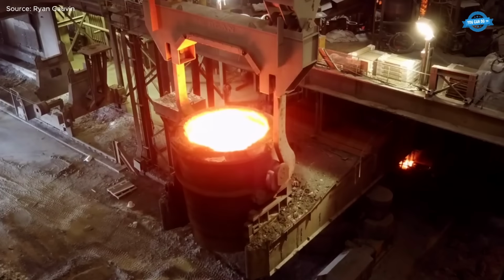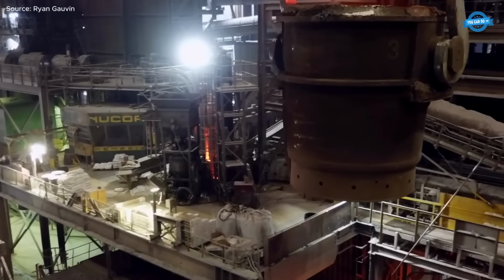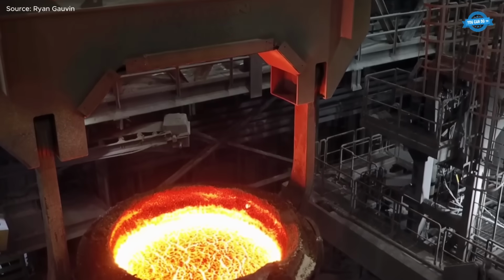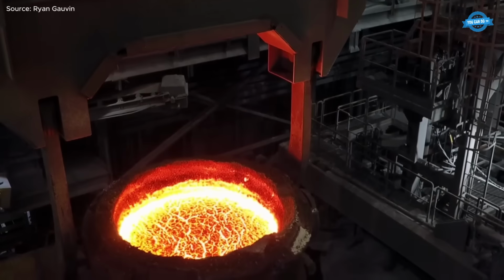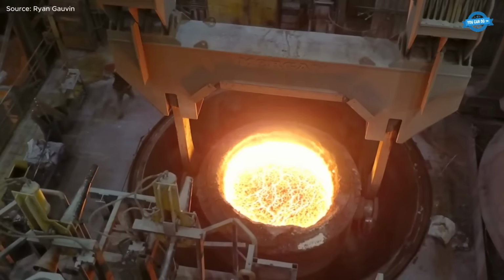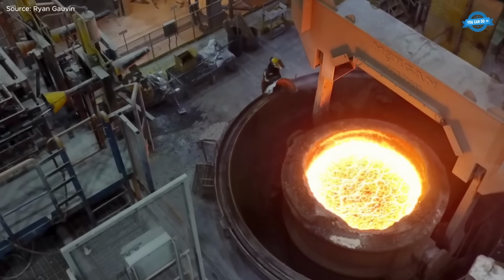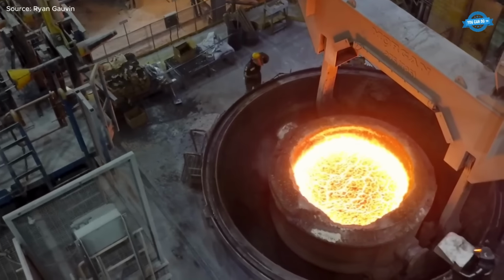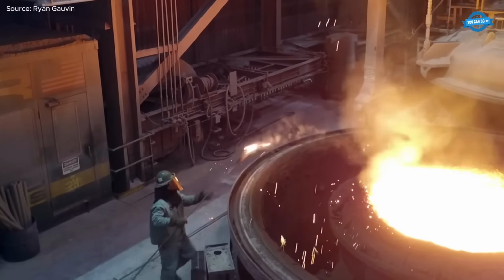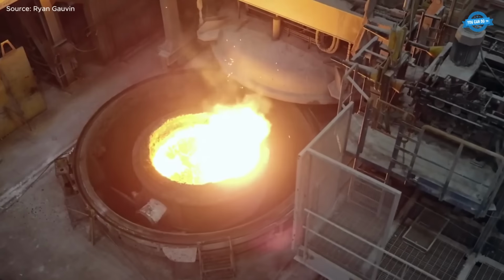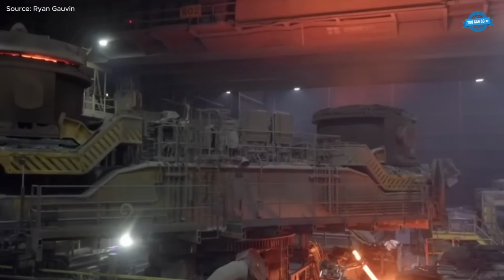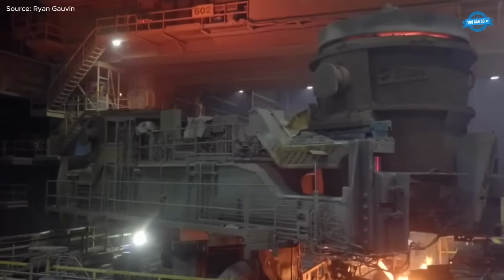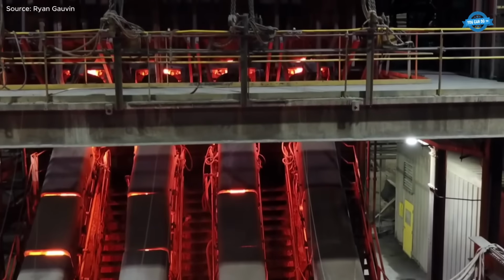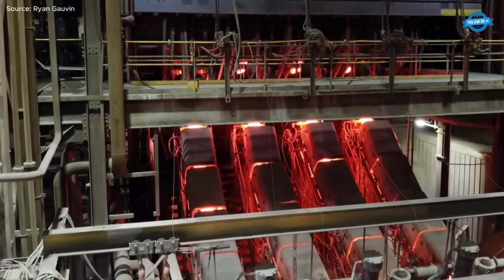Secondary metallurgy takes place at the ladle metallurgy furnace, where chemistry and temperature are precisely adjusted to meet specification. For demanding grades, the steel is further treated in a vacuum tank degasser to remove dissolved hydrogen and nitrogen, improving internal soundness. The ladle is then transferred to the continuous caster. A rotating turret exchanges empty and full ladles, feeding steel through a tundish into the mold to form solid blooms.